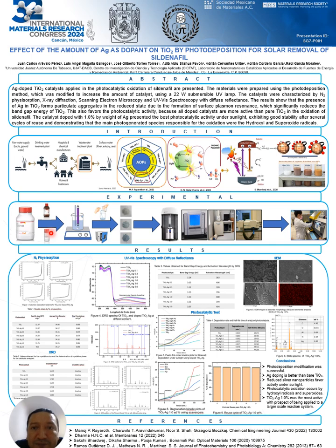The catalysts were prepared by photodeposition using a 1:1 water-isopropanol solution in which the necessary amount of silver was dissolved, and then the titanium dioxide powder was added. The system was stirred for 10 minutes and bubbled with nitrogen gas for 10 minutes. Then a submersible UV lamp was introduced for 60 minutes. The solvents were removed by decantation and the solid was dried in an oven at 120 degrees centigrade for 24 hours.